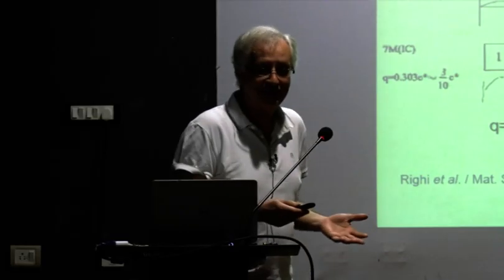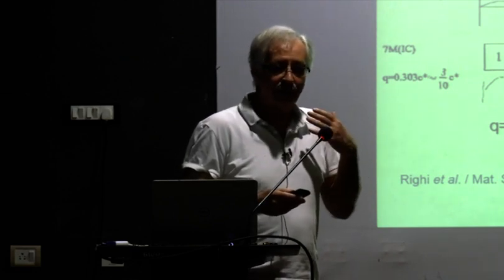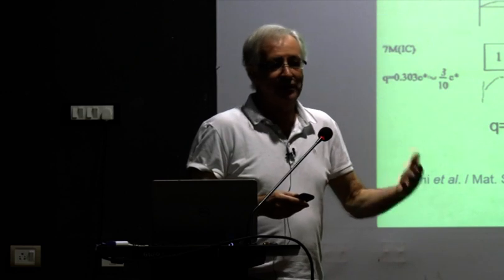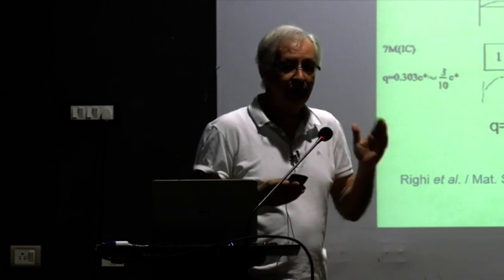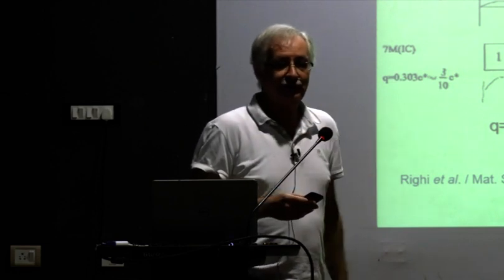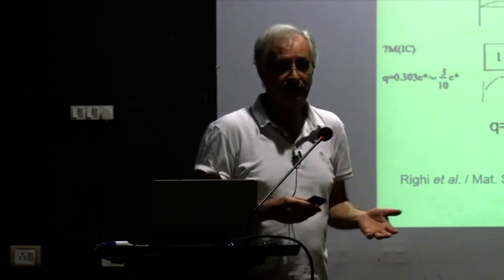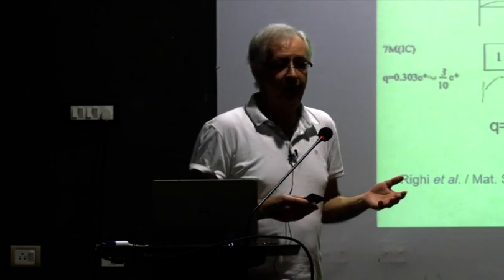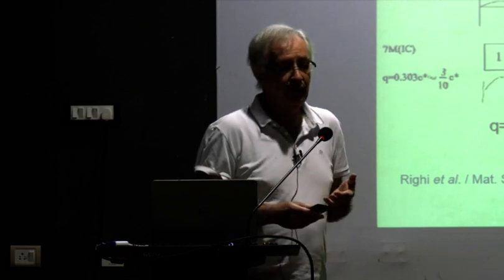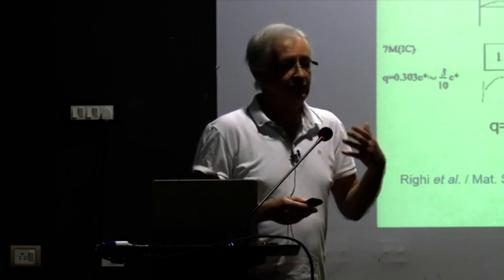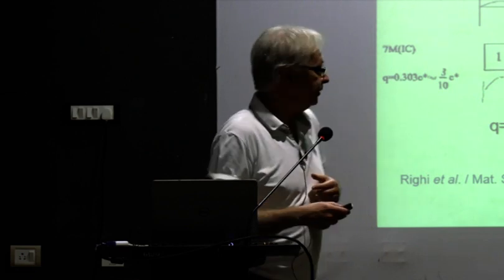Well, it's gone. It's very washy between 5M incommensurate and when you go to the 7Ms. It becomes very difficult to distinguish what is really 5M and what is 7M. It's a question of how the modulation vector changes. We extract the modulation vector from our refinement program, and then it delivers a value which we then have to play around with to understand what the periodicity is.